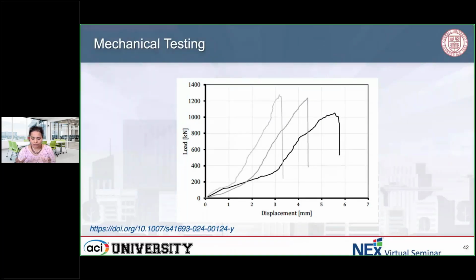Each structural element has a lot of variability. This is something people have seen with cube testing too. If you were to print layers and then take small cubes and cut them, there is a much higher coefficient of variance than you would see with cast samples. So this is something that's expected, but also in this case, this could mean that the crack patterns in each